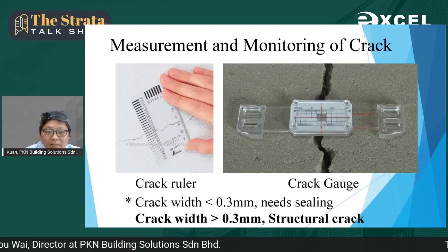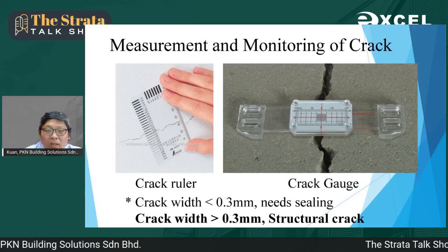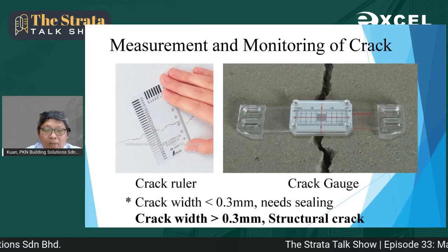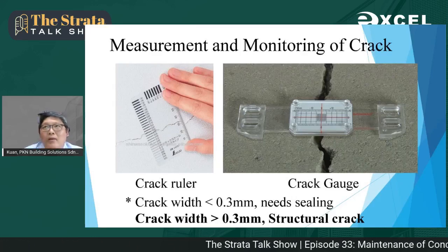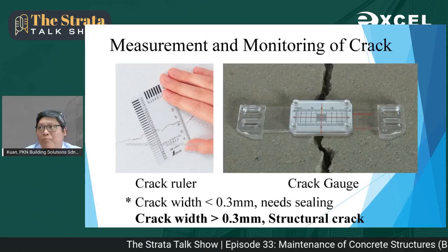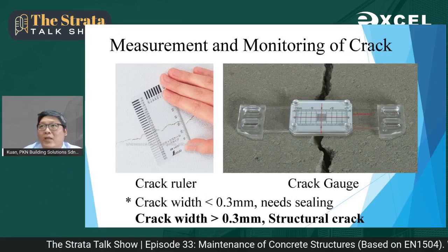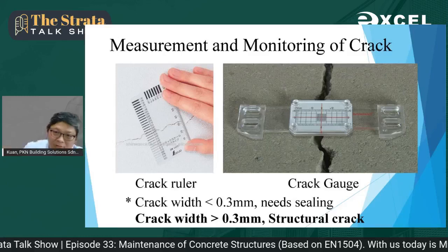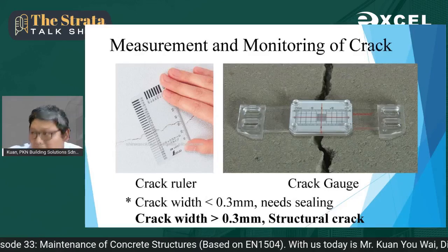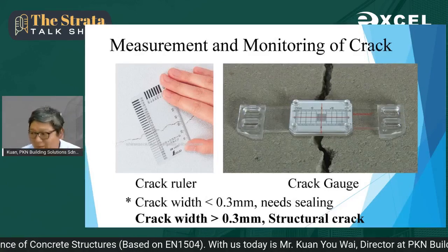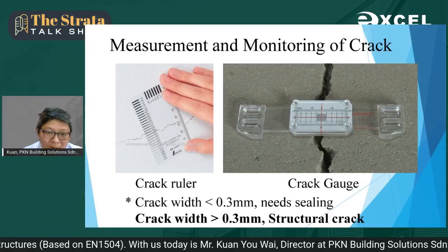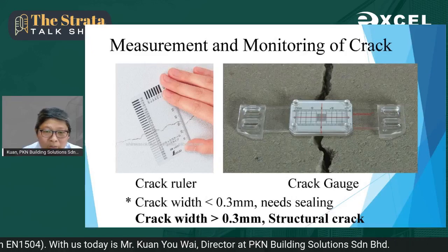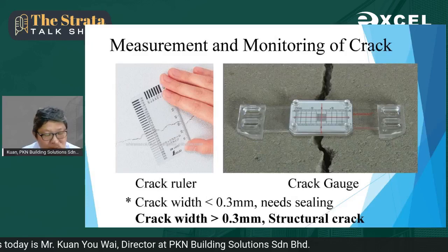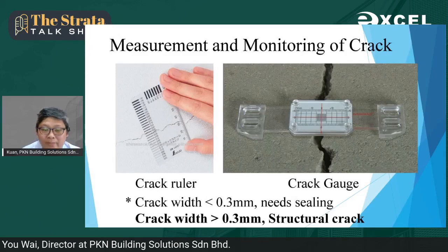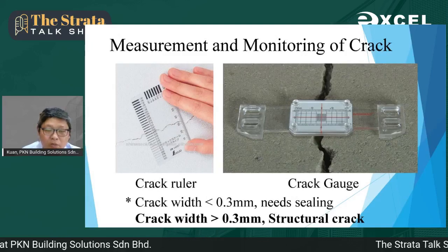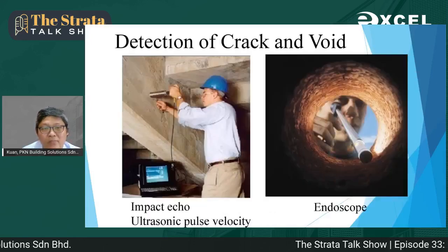And based on BS 8110, anything larger than 0.3 mm on the structural element, if it happens on your pillar, is even more severe. If it happens at the lower part of your building, the pillar in the basement is even more severe than the one above. So it all depends on the location and whether it is a primary beam or secondary beam, things like that. So it all depends on the load that it carries.